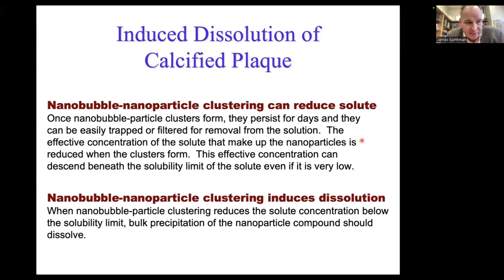So this is our strategy. We form these clusters. We can force the effective concentration of the solute down below the solubility limit and start dissolving it as much as we want, as long as we can keep adding more and more nanobubbles.